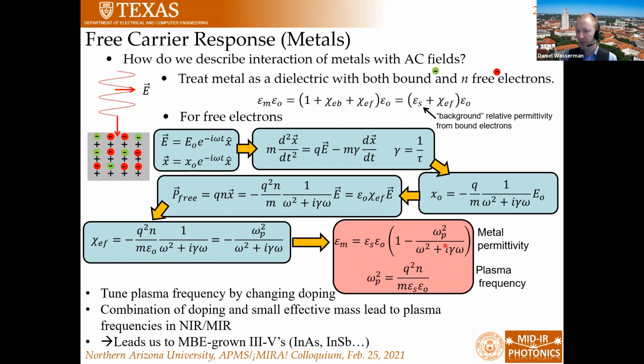What we see is a permittivity that at frequencies close to the plasma frequency, so when omega is approximately equal to omega p, is basically zero. And as omega gets smaller, that permittivity becomes negative, right? So we can find a material system where, if we can control the amount of free carriers we put in it, we can essentially control the permittivity, and we can make our own metals. Of course, the material system is semiconductors, because we know that we can dope semiconductors to have a certain amount of free carriers. I mean, that's what semiconductor doping is. In fact, we can control whether those carriers are electrons or holes, and we can control the density of our dopants, which controls the density of our free carriers.